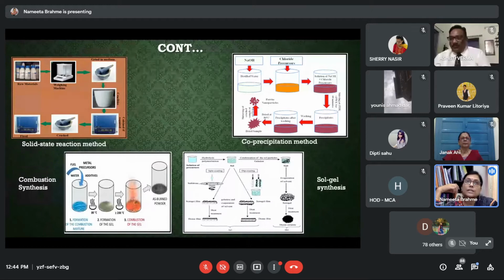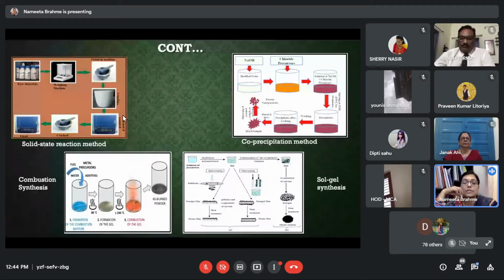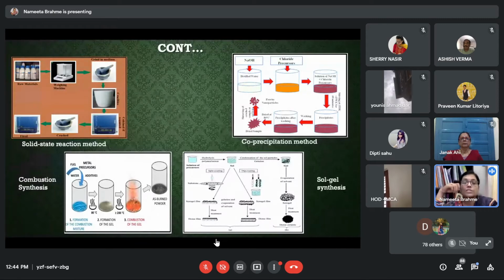And in solid state reaction, you have heard that flux is also used. Now, what is the use of flux in this reaction? Flux actually enhances the reaction rate, as the solid state reaction method requires high temperature ranging from 1100 to 1500 degree centigrade. And for getting better homogeneity during grinding, some organic volatile liquids are also added like acetone, alcohol, distilled water. In the presence of these volatile liquids, the raw materials are mixed properly and then fired at required temperature.